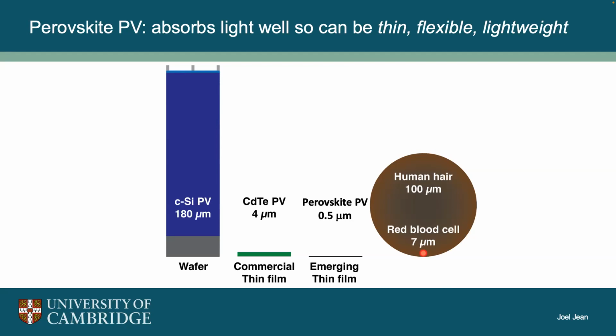Whereas if we look at the thin film technologies, and this is where they get the name, thin film technologies, cadmium telluride is something like 2 to 4 micrometers thick. And to harvest the same amount of light, the perovskites are 500 nanometers thick. So they're extremely thin. In fact, for reference here, a human hair is 100 microns. A red blood cell is 7 microns. This is the PV cell, just how thin it is. And so this is why it opens up applications in lightweight PV, and why, for example, crystalline silicon cells typically are quite heavy and bulky in comparison.